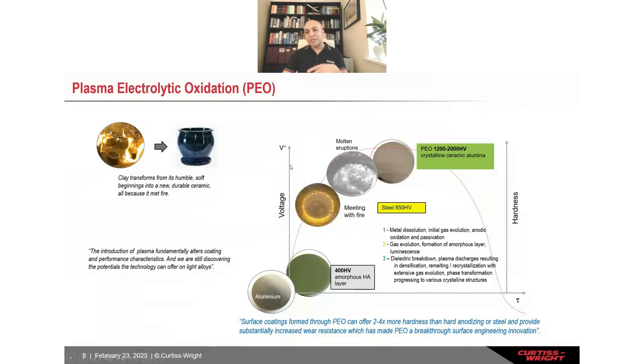On the right-hand side, you see the vertical axis is the voltage in the process, and the horizontal axis is the processing time. This is one side of the bipolar process, a positive cycle of the PEO process. You have got this aluminum at the bottom, and you start to have electrochemical reactions during the PEO process at lower voltages. Just like in hard anodizing, you start to dissolve the surface, create aluminum ions, and react with oxygen ions to form amorphous aluminum oxide.